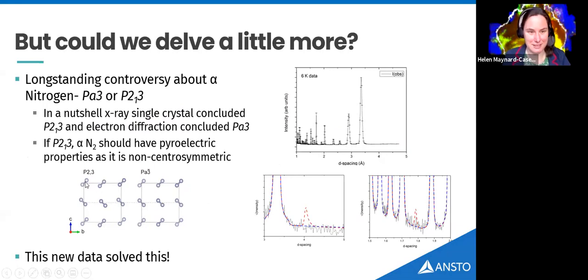It's very subtle. It's around where these molecules are actually centered on the origin. So the pervading structure had them slightly off-center to the origin, and the structure that I've proven it has to be is actually centered. It's quite important because if you have this uncentered structure, it imposes pyroelectric properties onto the nitrogen, which could have been very interesting. But fortunately for Pluto, we found that it's actually the simpler symmetric structure. And there's some information as to why that is. It comes down to there should be peaks here and here if it is the asymmetric structure, and there just aren't those peaks.